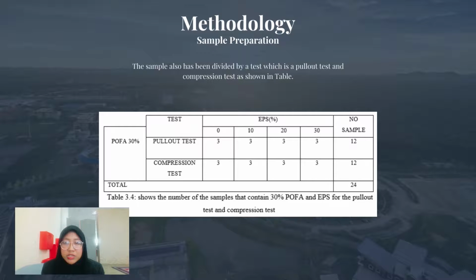For the methodology sample preparation, it is divided by test, which is the pull-out test and the compression test, shown in the table. Here, shown in the table is the 30% POFA, and EPS from 0% till 30% EPS, and the number of each sample is 12. If you total the pull-out test and compression test, it will be 24 samples.